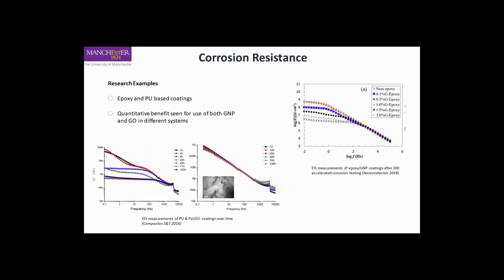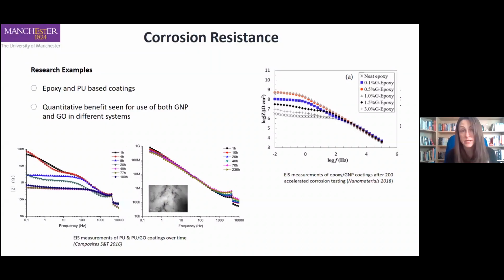So lots of groups have shown how graphene affects coatings quantitatively through electrochemical measurements. And EIS is electrochemical impedance spectroscopy, and it's a technique that essentially measures the ability of a coating to impede the flow of current, and it's directly related to corrosion. And the easiest way to compare the effects with different coatings is to compare different values for the impedance modulus. There's a few examples from the literature I've just put in here.